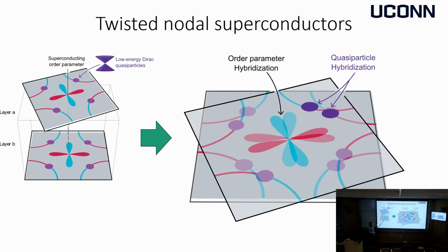Each superconducting layer has an order parameter, and it has electrons, which, affected by the order parameter, form Dirac quasiparticles around specific points in the Brillouin zone. And in principle, it's all an interacting problem. Order parameter affects the quasiparticles, quasiparticles affect the order parameter. But what I'm going to do for simplicity in the remainder of the talk is treat the properties of these two objects a little bit separately. So first, I'm going to focus on what happens in a twisted interface of such unconventional nodal superconductors, what happens with the order parameters. And in the second part of my talk, I'm going to talk about what happens to the quasiparticles. The assumption behind that is that the coupling between these two, order parameters and quasiparticles, across the interface is weaker than the intrinsic scale of superconductivity, which is okay for high TC superconductors where superconductivity is really strong.